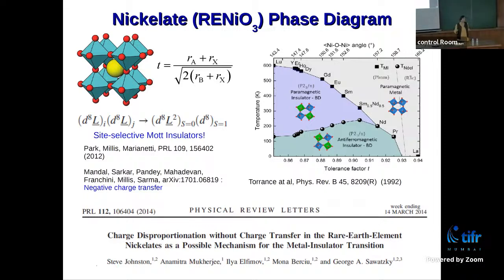Nickel remains d8. It doesn't go anywhere. Rather, you have a ligand hole, that means a hole at the oxygen side. So what you call d7 is actually d8 with a ligand hole. And you have two such objects. What you form is that one of the nickels acquires two of the ligand holes and forms this S = 0 object, and another one remains devoid of the ligand hole.